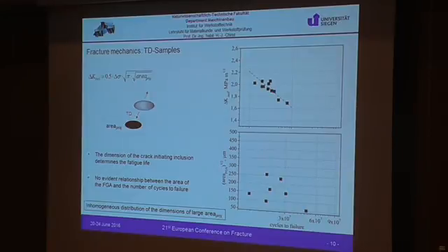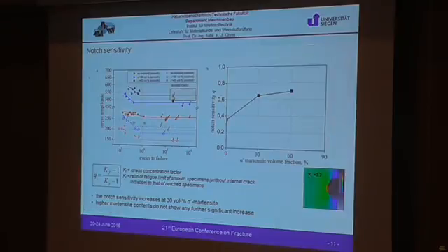We can conclude that, at least for TD samples, the dimension of the inclusion, the applied stress, and the notch sensitivity of the microstructure are the main parameters controlling the fatigue life in the VHCF regime of predeformed metastable austenitic stainless steels. In order to have a quantitative idea about the notch sensitivity of the microstructure, I performed tests with a smooth specimen and a notched specimen with a K_t value of 3.2. And the fatigue results are presented in this graph. The calculated notch sensitivity showed that already at 30% martensite, the notch sensitivity increased very much, whereas a further increase in martensite content doesn't result in an even stronger increase of notch sensitivity.